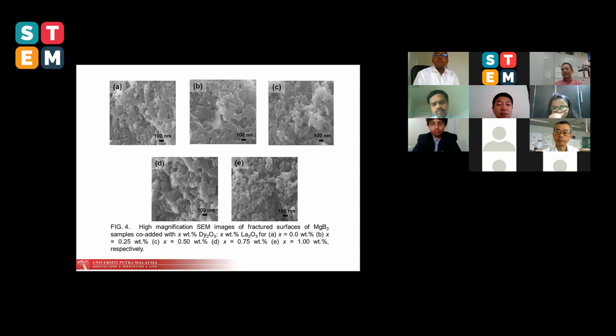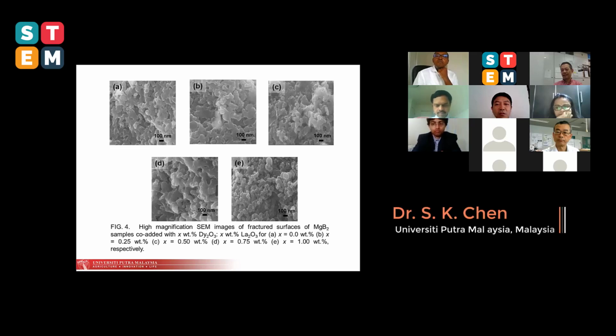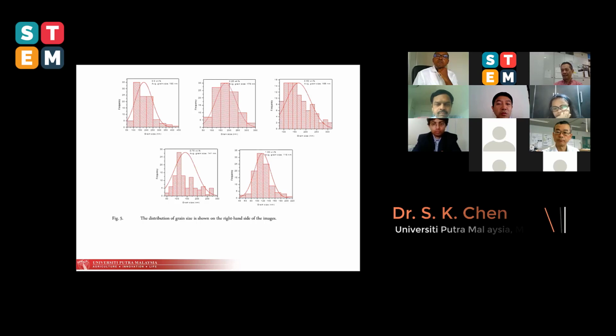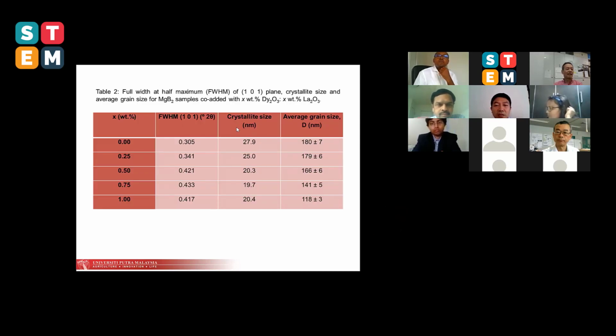These are the high magnification SEM images. The purpose of capturing those images is to calculate the grain size, which I'm going to show you in this table here. Crystallite size we calculate using the Scherrer equation. That is the average grain size that we calculated based on the SEM images. The average grain size decreased with the co-addition amount of the dopants, as we expected, because as we reported previously, dysprosium oxide or lanthanum oxide alone added into MgB2 decreased the grain size. So this is consistent with the previous result.